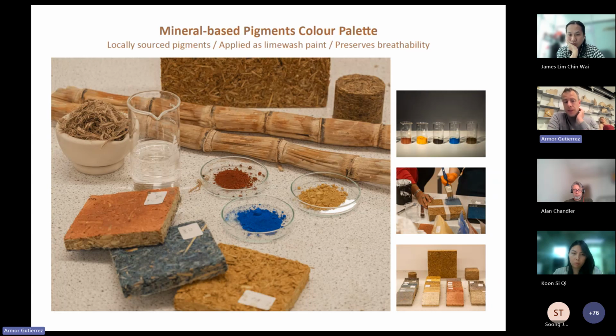We use mineral pigments, clay-based pigments, to coat. Some of them were coating the material in these 3 samples that you see at the bottom. The first one is just a render, which was a lime wash with the color applied to the surface, whereas the second and the third one were mixed with the fiber itself, just to create color going across. Both of them work quite well. We are more inclined to test what happens with this option, so you can control more the finish and the color. And you can see here all the components that we put together.